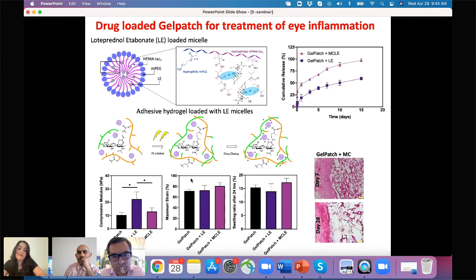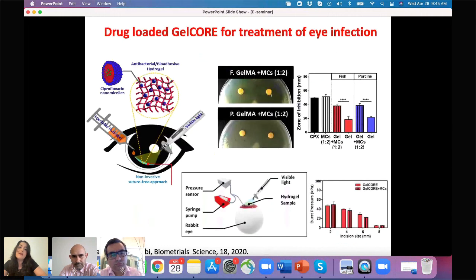We also look into the different physical properties of gel patch. Our goal was to see not significant changes in the adhesion and mechanical properties of the gel patch once we introduce our nanoparticles. And we also did in vivo test using subcutaneous implantation model to see the degradation rate of these gel patch formulation containing drug over time, and also look at the inflammation and in vivo biocompatibility of this formulation. So now we are testing this hydrogel in animals with inflamed eye to see their efficacy in treatment of eye inflammation. We also did some work on making this hydrogel in a way that they can be used for treatment of the infected eye.